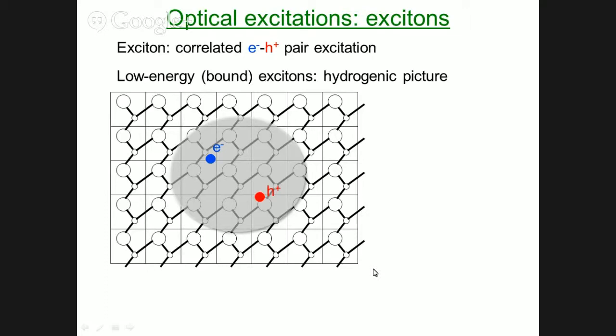Excitons in something like silicon are not very important, but in all polymers and wider bandgap materials, they're extremely important because that's what the light turns into. So when chemists talk about excitons moving around and diffusing to an interface, where I'm going to harvest the energy, we're talking about electrons and holes that were created by light, and they're sort of stuck together as a package.